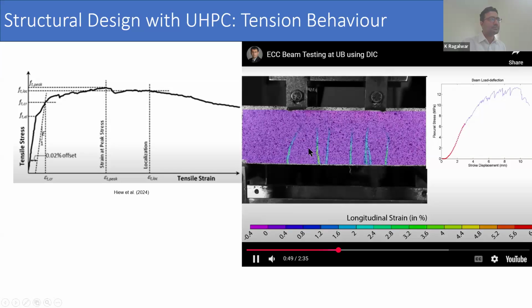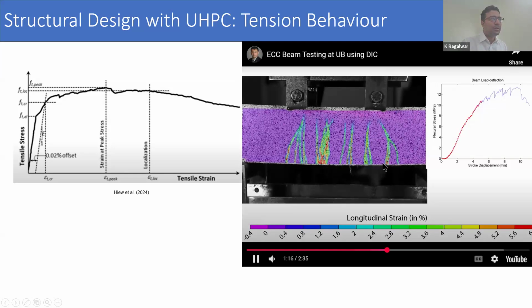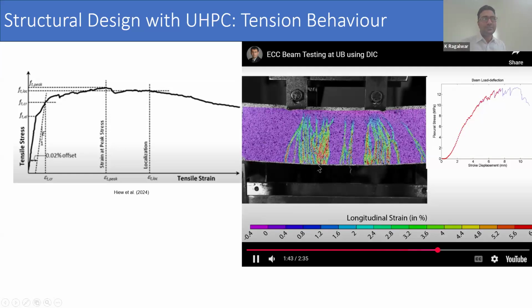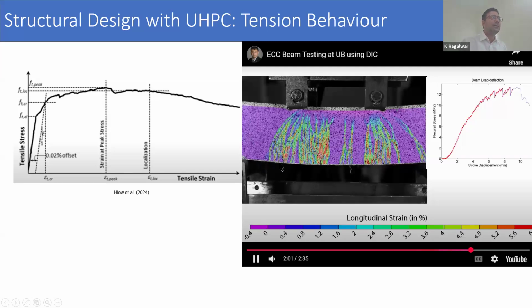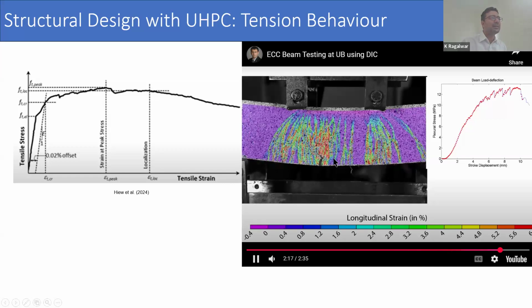So this is where the first crack appears. You would see cracks propagating up to what is probably the neutral axis depth. And in this location, you would see that all these cracks are forming, but they are still being bridged by the fibers that are crossing. And that bridging capacity is sufficient for another crack to develop. And when you have really high bridging capacity, along with lower fracture toughness of the concrete, that helps concrete form multiple cracking. And because of this multiple cracking, it shows what is known as pseudo strain hardening behavior.